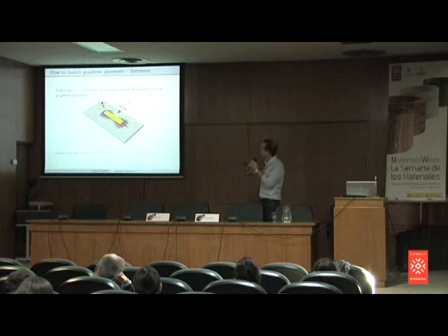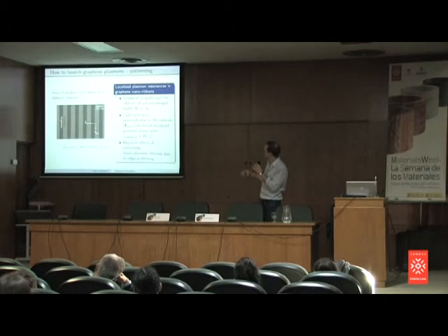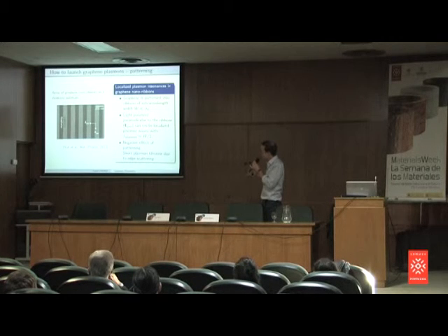And another approach, much more simple, actually, is not to put anything there, but simply to cut the graphene itself. Remember, we need small structures. Well, then let's make the graphene small. This is from the IBM group. What you see here are graphene ribbons. This is graphene substrate, and these ribbons here are, well, a few nanometers, 100 nanometers, let's say. And then what happens again, if you shine light with polarization like this, then you excite in this ribbon a standing electron wave, and that's your plasmon. And that's from the IBM group in New York.